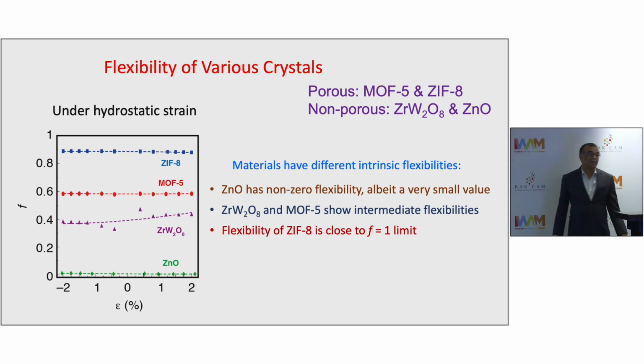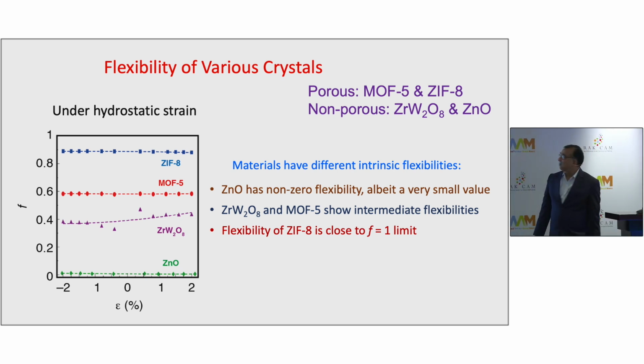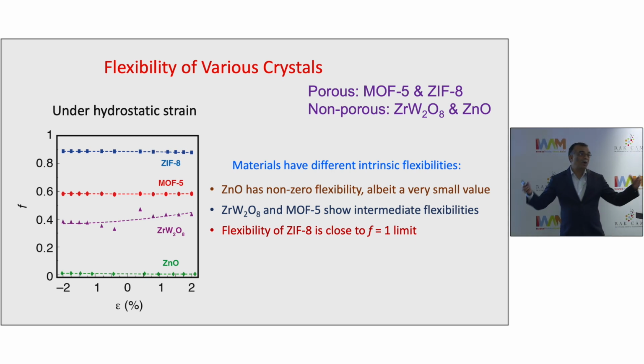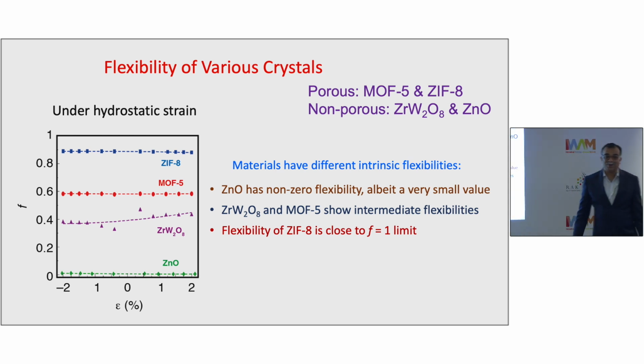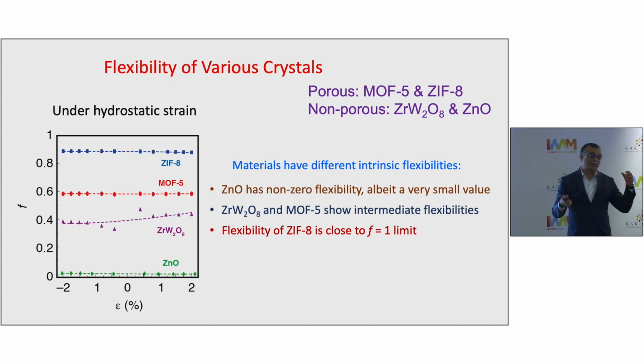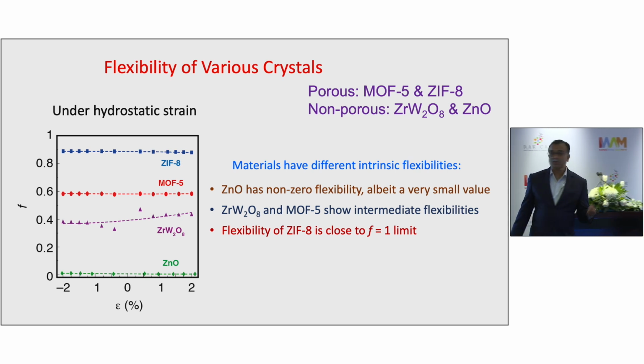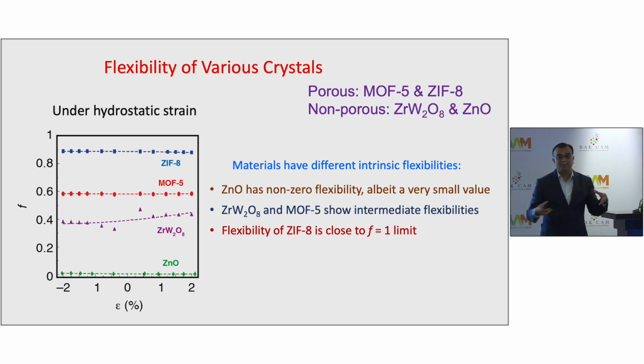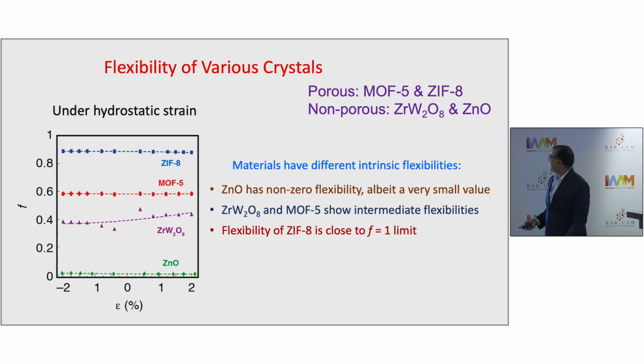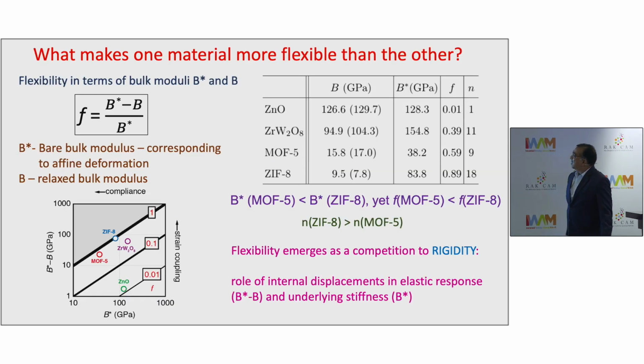And then we use first principles calculations to determine the flexibility of a variety of crystals, and you will see here, this is in response to hydrostatic strain. You will see ZIF8 falls very close to 1, and zinc oxide, which is a very simple crystal structure, wurtzite, with only one internal structural parameter, has very low flexibility because when you apply compression, only 1 degree of freedom gives rise to that. Okay, so this fits the intuitive picture we have about the flexibility of these solids. What makes one material more flexible than the other?